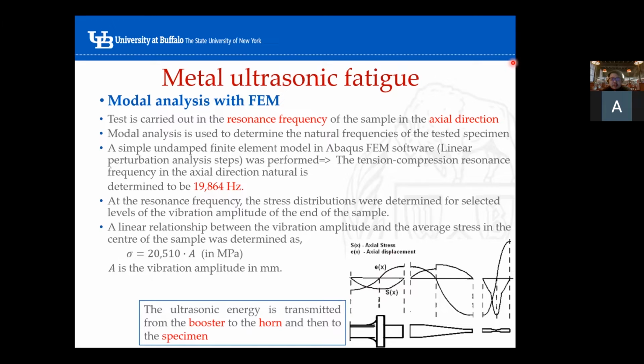So this test actually consists of 3 different parts. First we have this component called the booster. The booster is used to generate a vibration amplitude, a displacement amplitude here. And the ultrasonic energy is transmitted from this booster to the horn, all the way to the final sample. So this is our sample.